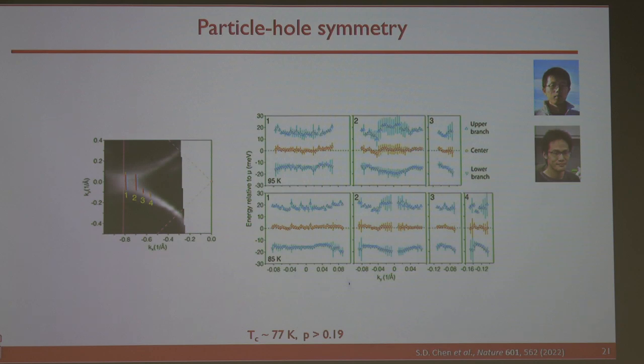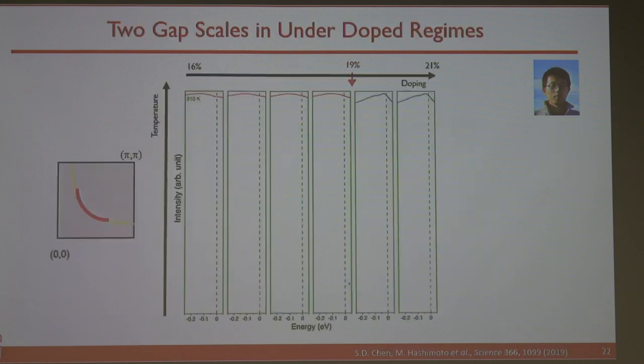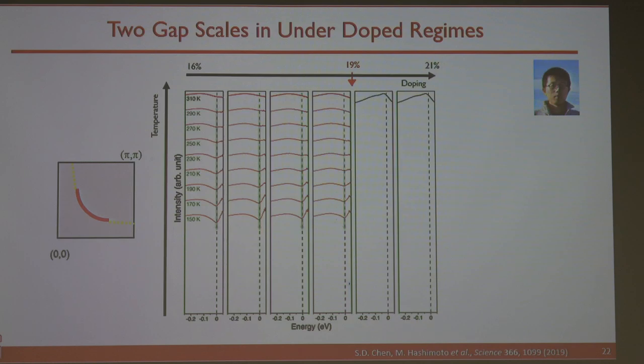So far I'm telling you about a gap in the overdoped regime. Okay. Now, showing you data. It's a relatively narrow, 5% doping range. Here's the 19%, that's it. Now, if you are below the 19% doping, you see a spectrum that looks like this, okay? Different doping. In a nutshell, as I go to lower and lower temperature, I hope you will be convinced that the dashed line is the chemical potential. But at lower and lower temperature, even well above TC, you see a suppression of density of states near the chemical potential. Okay.